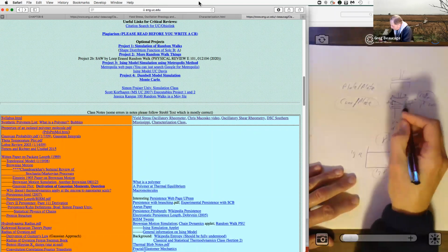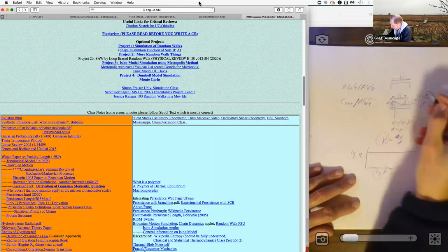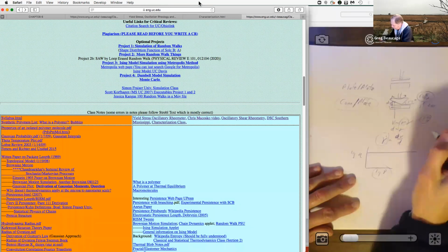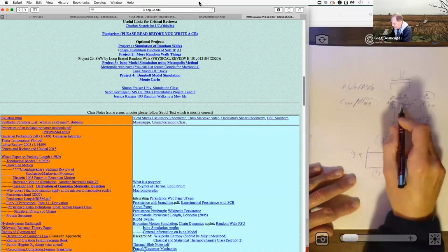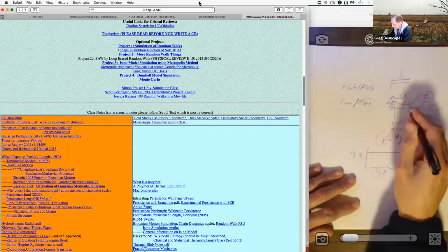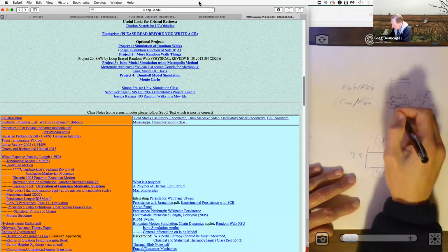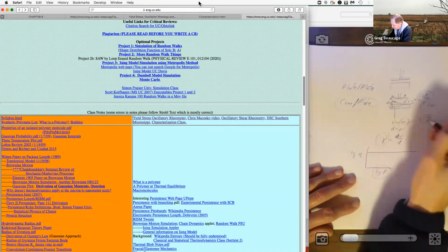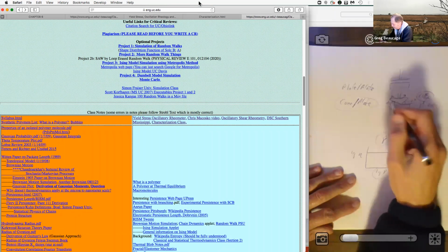The strain amplitude, the amount that you turn this thing, is going to be about 1%. So it's basically not moving much to look at. It's vibrating. This thing's really just vibrating to get the rheology. And that's the normal way to do polymer rheology, because if you strain it too much, you deform the fluid. You don't want to deform the structure of the fluid. You want a low strain to maintain the fluid undeformed. So an oscillatory measurement with 1% strain at something like 60 hertz is the normal thing that's going to happen.